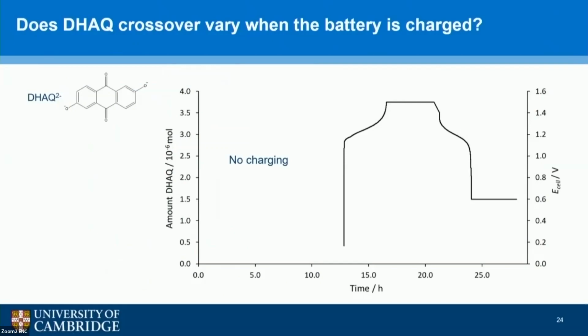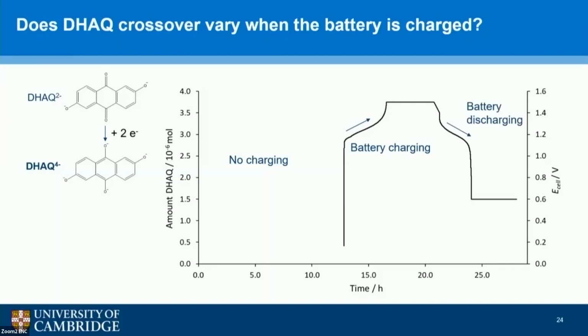Firstly, we have no charging. So you can see I haven't got the cell voltage here. And this is just to get a background permeability as we did before. Then we charge the battery, and the idea here is that we're now going to the 4- state, and then we hold the potential here for a while to see if we can see a difference in the crossover rate when the battery is fully charged. And then at the end, we're just doing the opposite. We're discharging the battery and going back to the 2- state.